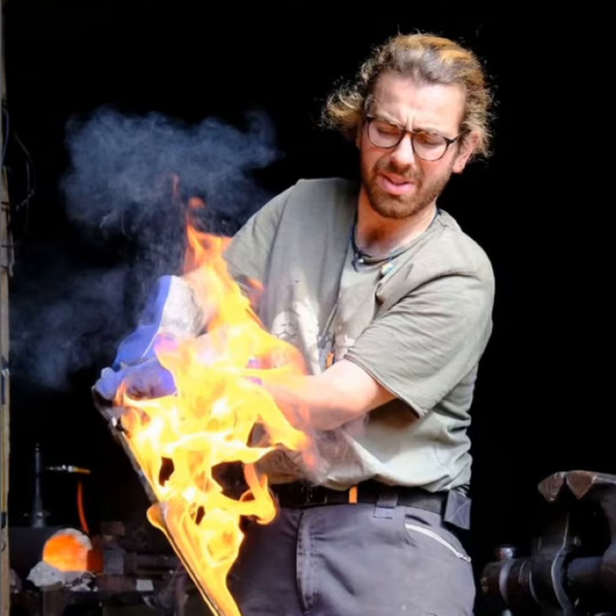So I personally do grind when I do some stone finishing. I leave the edge thickness, I grind it down, but not too much, and then I do the rest of the material removing with the stone, so it stays cool and the HRC is not decreased by excessive heat that is introduced to the blade. And you can remove material really until there's a burr on the edge, with only the two blade sides running into each other, basically like a Scandi grind. And for performance, this is really the best you can ask for, I think. And this also improves performance by a little bit, I guess.